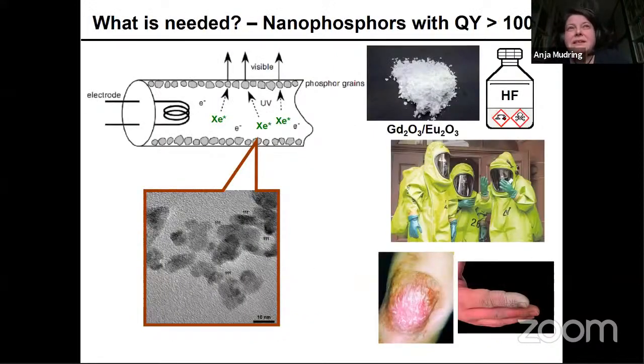And we were at that time, I honestly have to say, innocent enough just to give it a try and make nanomaterials. The problem is with all this, you have to have a material that is absolutely oxygen-free, because any oxygen in the material opens up a pathway again for radiationless decay. And that's something we don't want to have. The other question is, how do you make fluoride nanoparticles that are absolutely free of oxygen? Well, in the literature you find you take a mixture of the oxides and treat them with HF. That might work in the lab, but in large scale production, that's probably not the smartest idea to do.